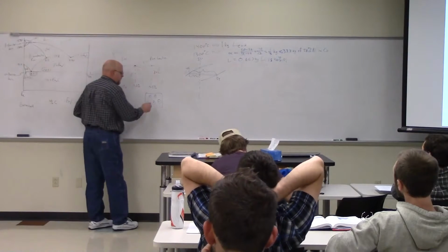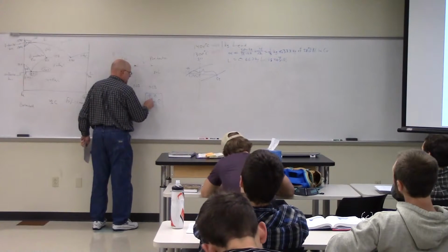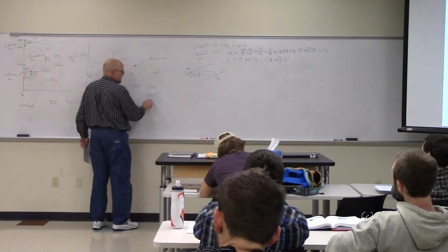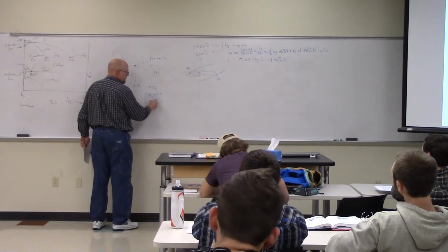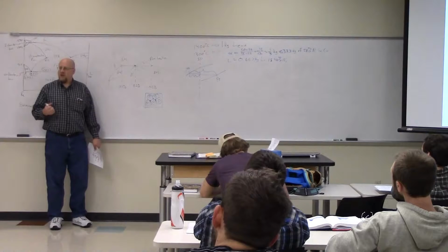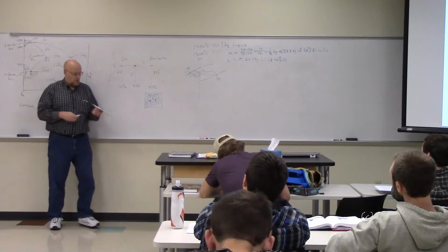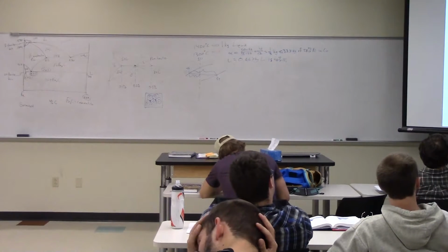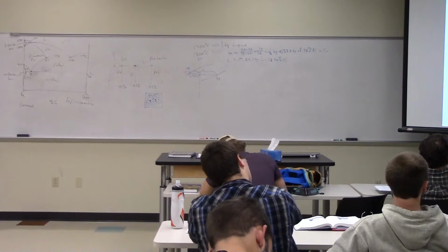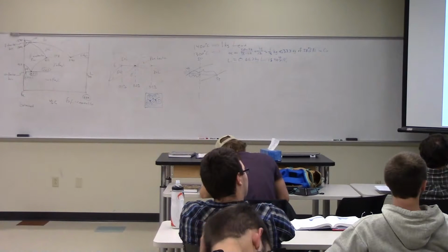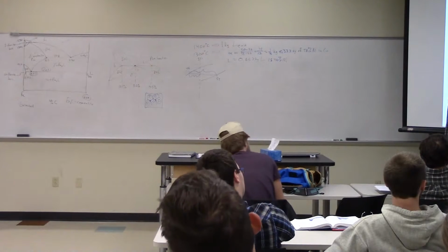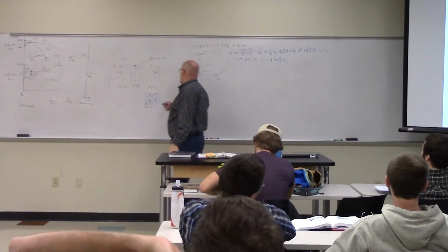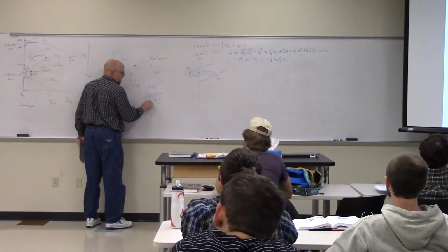So if I were to take a sample, they'll continue to grow until they almost fill all the space. So there's just a little bit of liquid left. There's still liquid in the spaces in between. But the solids have begun to encroach upon each other. At that point, when I'm almost all solid, right here, the little bit of liquid that's left is very copper rich. So once that solidifies, I end up with a lot of copper here.